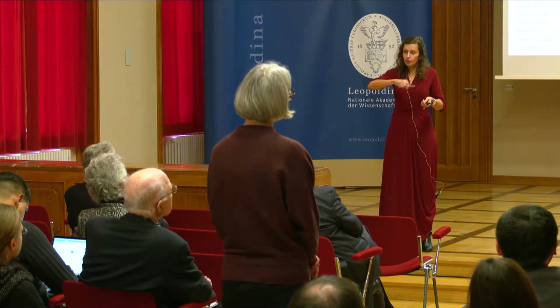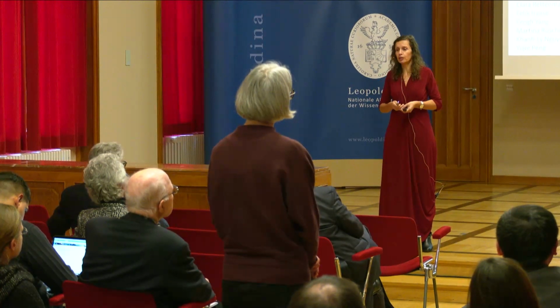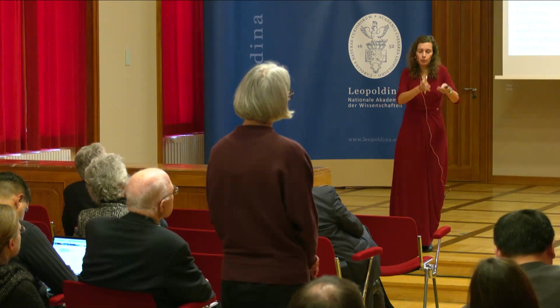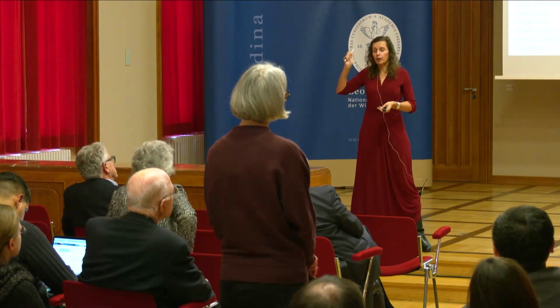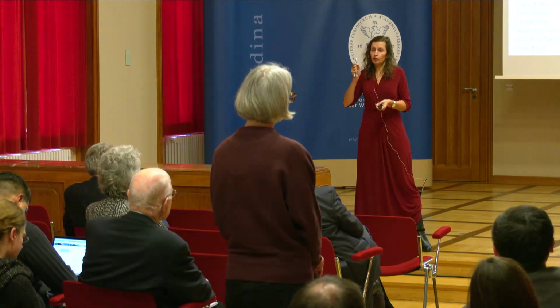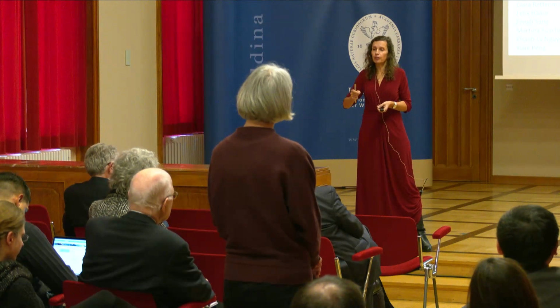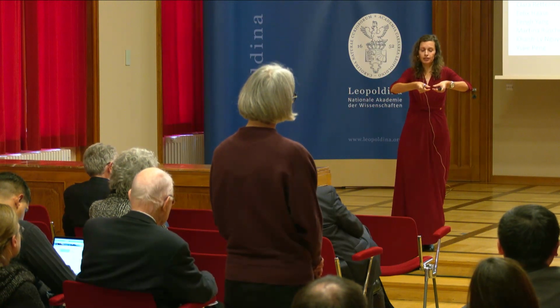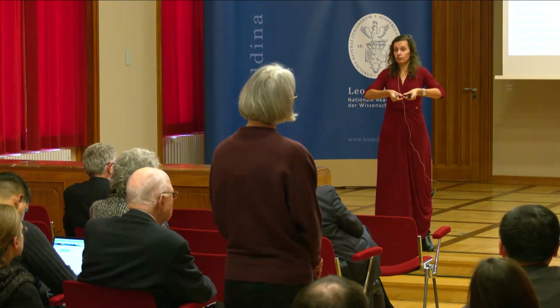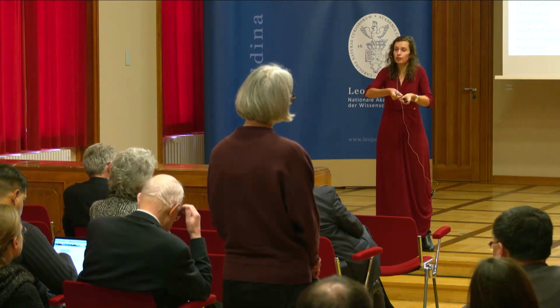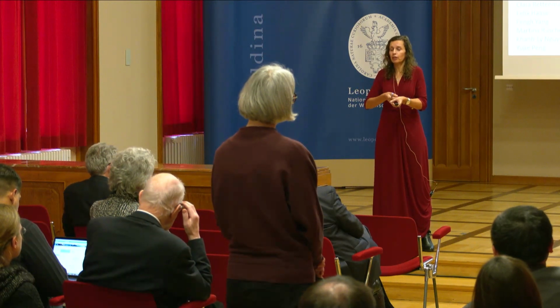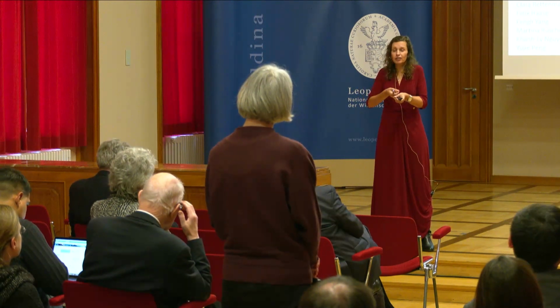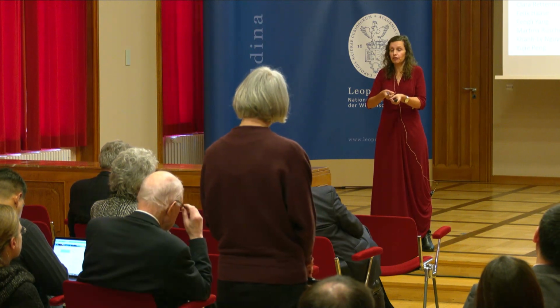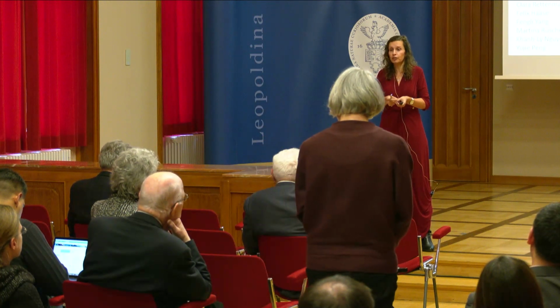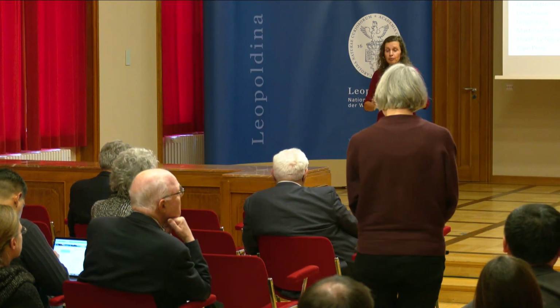So the restructuring is also being looked at in theory, but I think you need to divide the problem step by step. When we're looking at thin films or single crystals, you can work very nicely with theory, because I can tell that my active catalyst has this surface termination. At least they know which exact composition I start with and the surface termination. But if I tell the theorist, calculate how much leaching I'm going to get from this material with this perfect initial surface composition in an electrolyte, that gets much harder.